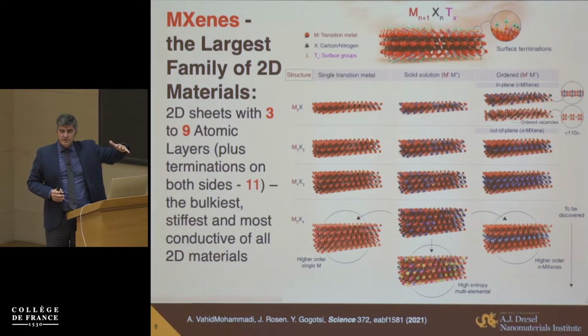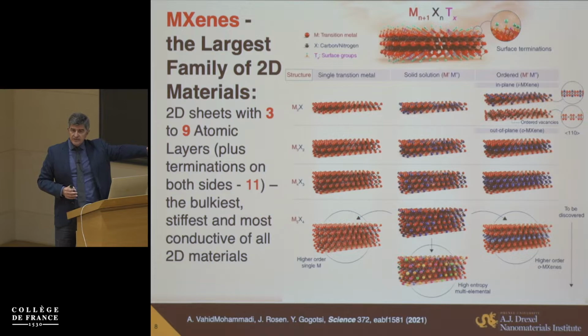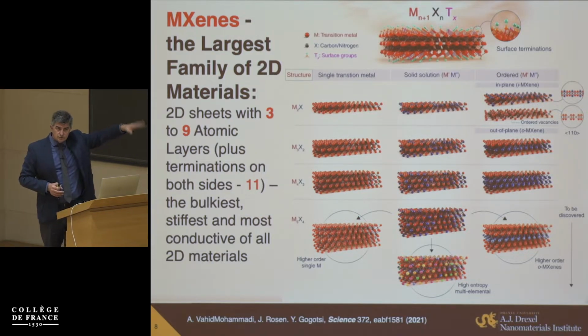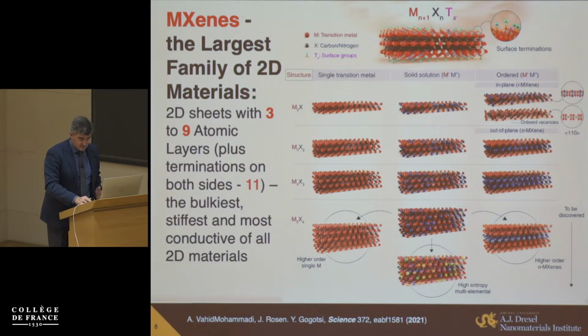Bending modulus is enormously, orders of magnitude, higher compared to graphene. So you can get straight layers which will not collapse, not flimsy like other thinner materials. But each of them will have this thickness here.